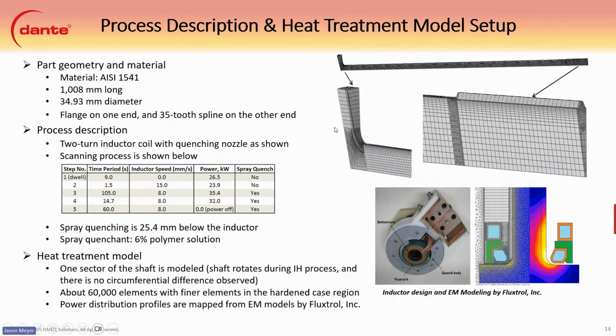And then, when we model it, they give us the process description. This is a two-turn inductor coil with quenching nozzles, as shown at the bottom here. You can see these hopefully on your screen. They're very tiny, but basically the inductor goes through, and then the spray trails it to quench the martensite afterwards. The process here includes a dwell at the beginning, and then a quick jump in speed, and then an averaging of the speed and spray throughout the process. The spray quench is about an inch below the inductor, and then the quenching is a 6% polymer solution that was used.